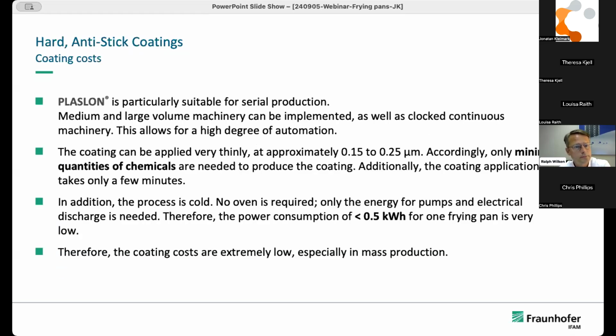Next slide, please. Now we come to the coating costs. The Plaslon coating is particularly suitable for serial production. Also medium and large volume machinery can be implemented, as well as clock continuous machinery. This is especially interesting if it comes to high volume production, so that we end up with a very high degree of automation. Concerning the coating, we apply only very little amount of coating thickness, so it's about 150 to 250 nanometers, and therefore we only need minimal quantities of chemicals.